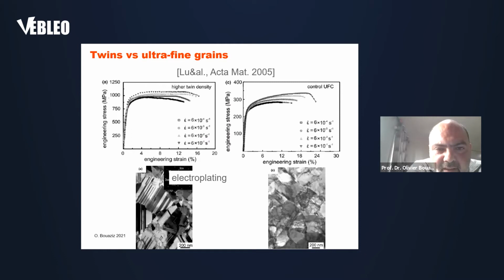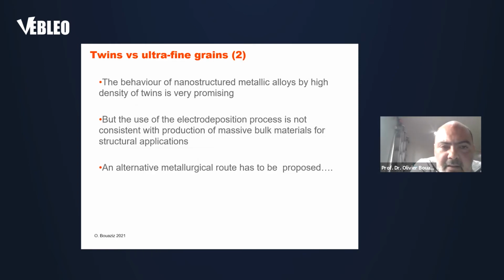So in 2005, Lu et al. showed something interesting. By electroplating copper, they obtained copper with a high density of twins, and the mechanical properties are strongly improved for the copper. So it seems that the behavior of nanostructured metallic alloys with a high density of twins is very promising, but the use of an electrodeposition process is not consistent with the production of massive bulk materials for structural applications. So an alternative metallurgical route has to be proposed.